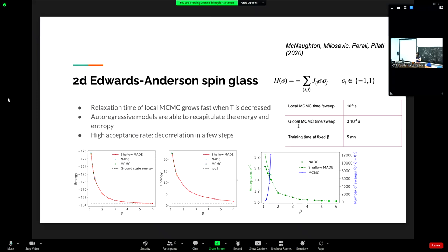And if you look at the acceptance rates, it's the inverse of the acceptance on the graph. You see that it's going to one, meaning that basically you are accepting every move. And so that means that you are more or less decorrelating in one step. And you see local MCMC probably needs millions of steps to decorrelate in this region. So there is a real gain of computational time. And also you can actually sample regions where you cannot sample using local MCMC.